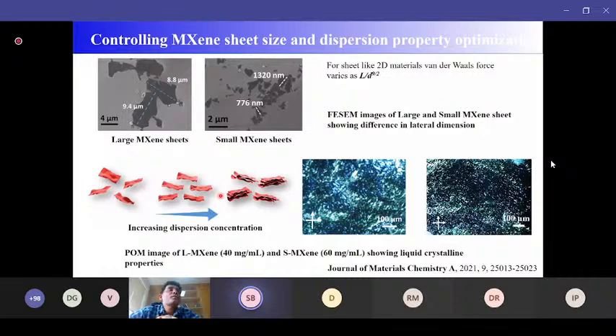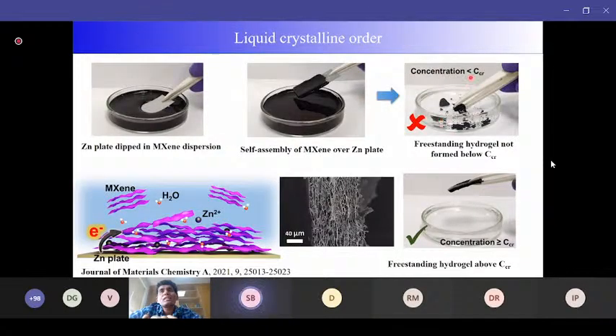This is the fact for any of the anisotropic materials. When the dispersion concentration goes above a critical concentration, they show some spontaneous ordering. So if we can make some kind of spontaneous ordering in the solution, we thought that if we put some zinc foil, they will assemble in a more ordered fashion, and with the higher interaction because of this increased L and lesser D. So with the expectation, as you can find, whenever the concentration is below certain critical concentration, we are not getting any freestanding hydrogel. So these are brittle, but whenever we go above a certain critical concentration, we are getting some freestanding hydrogel.